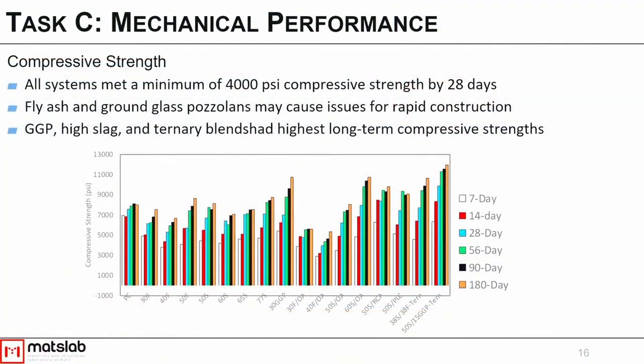Here's an example of our mechanical performance. This is our compressive strength. So we looked at compressive strength over 180 days. All of our systems had a minimum of 4,000 PSI. That was sort of our minimum requirement for strength at 28 days. All of them met that or exceeded it.